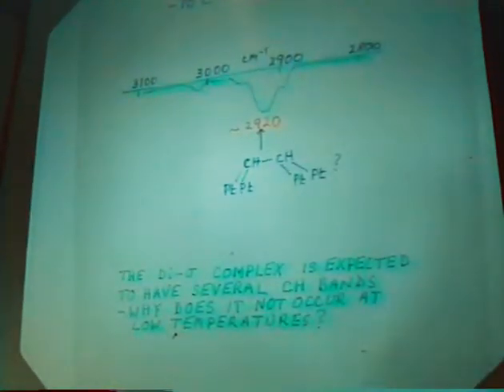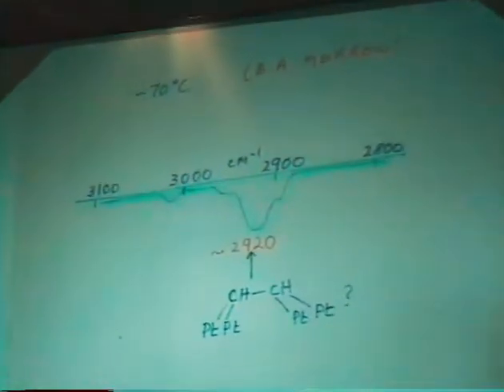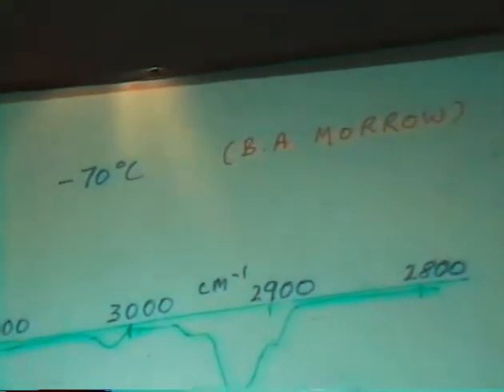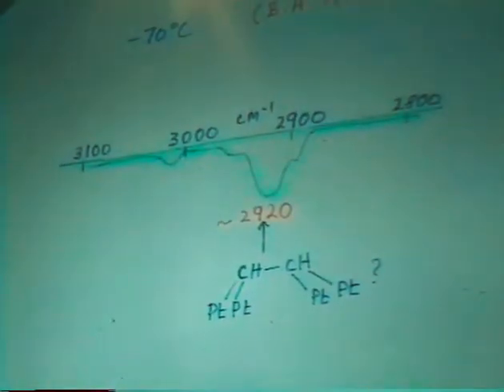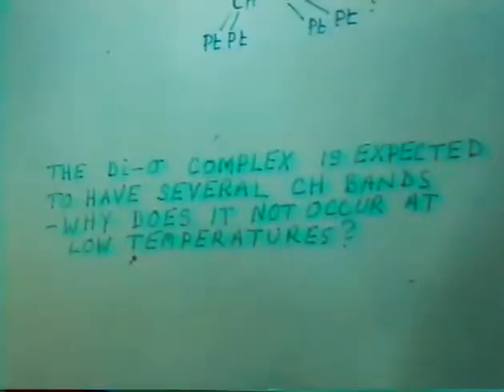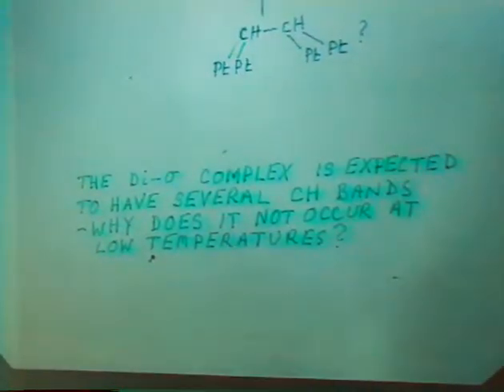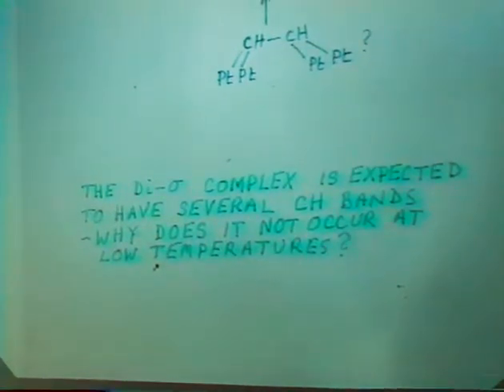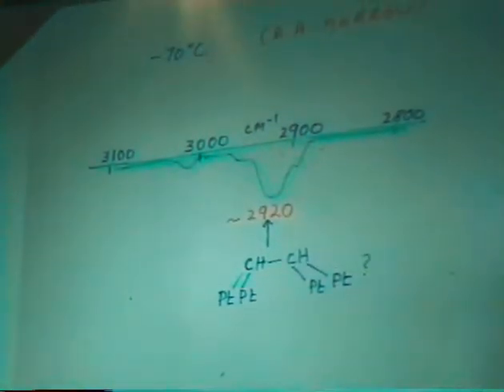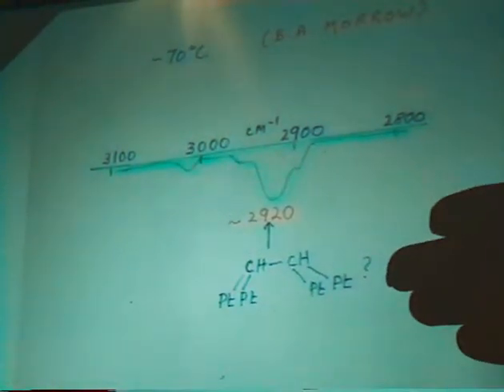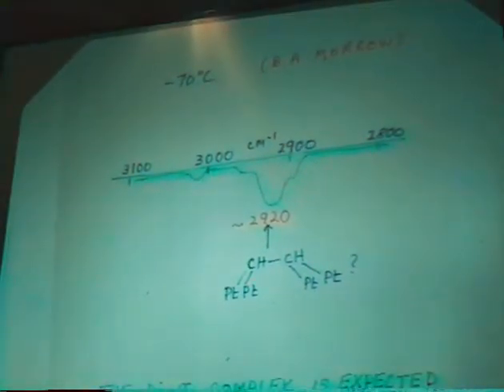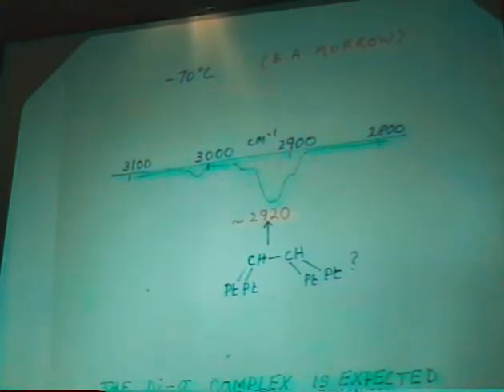Barry Morrow then did an experiment at low temperature and got a notably simplified spectrum, with a single strong band in the alkane region. And this surprised us, because if we had the di-sigma complex, which we would have expected at low temperatures, that has four CH bonds. How can it only give one CH bond stretching fundamental? So we assigned that, with some grumbling in the paper, to an alkane species with single hydrogens on a carbon atom. There, in principle, there could be two fundamentals, but one of them might reasonably be weak.